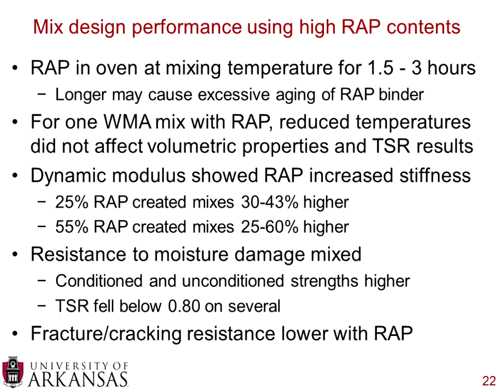Now, they did several RAP mixtures, and for one of the RAP mixtures, they did use warm mix asphalt, and they found out that reducing that temperature did not affect volumetric properties or TSR, which is tensile strength ratio results. If you recall, one of the recommendations was to do moisture testing on RAP mixtures. And the TSR, the tensile strength ratio, that test compares moisture conditioned to unconditioned samples. And for the one warm mix asphalt mixture that they evaluated with RAP, they found that there weren't any problems with that, which is encouraging.